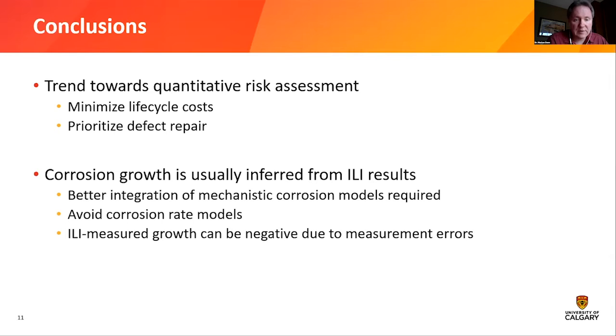From a temporal uncertainty perspective, we should avoid corrosion rate models. They don't really accurately represent the temporal growth over time. And it is possible that based on the ILI measured growth, this can be negative, and this is due to the strong influence of measurement errors. So that doesn't mean there's no growth. It just means the measurement error is so significant there can still be a small or even quite a significant positive corrosion growth of the actual defect.